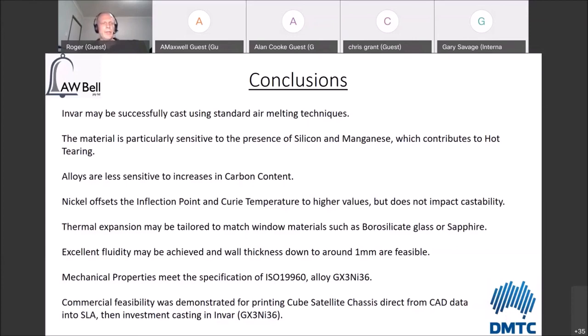The material has quite an extraordinary fluidity, and you can achieve wall thicknesses down to around 1 millimeter in an investment casting. All of the mechanical properties we looked at for the different nickel specifications met the requirements of the ISO standard for the alloy GX3 nickel 36. And we were able to demonstrate commercial feasibility for printing cube satellite chassis direct from CAD data into SLA, and then investment casting these into Invar.